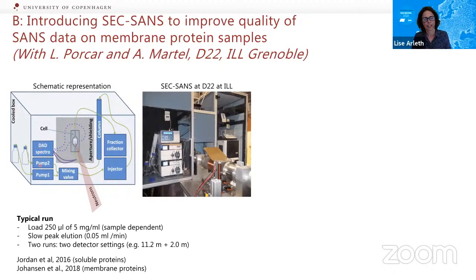So we basically mix our samples, and then we run it through the size exclusion chromatography column, which sorts it according to the different molar masses or different sizes of the particles. They are then sent into the sample cell where they are investigated by the neutrons. So this is a technique that has been around for almost 15 years with X-rays, but it was very new that Anne Martel and Lionel Porcar showed in this article by Jordan et al. in 2016 that they could also use it in combination with small angle neutron scattering.